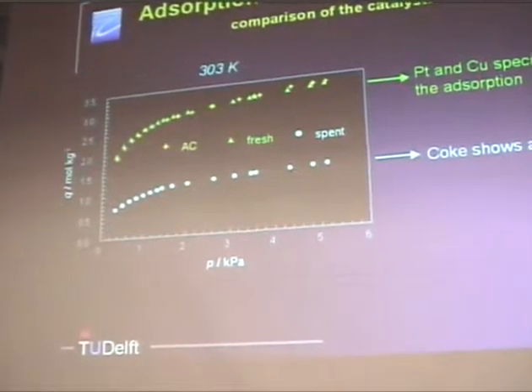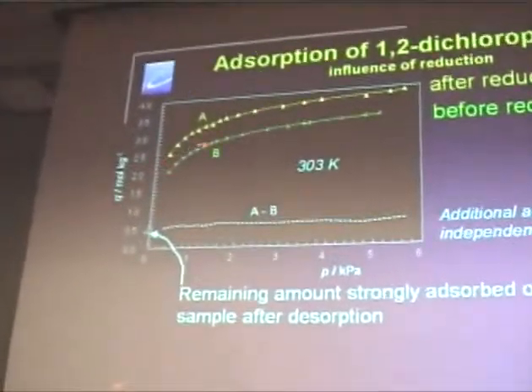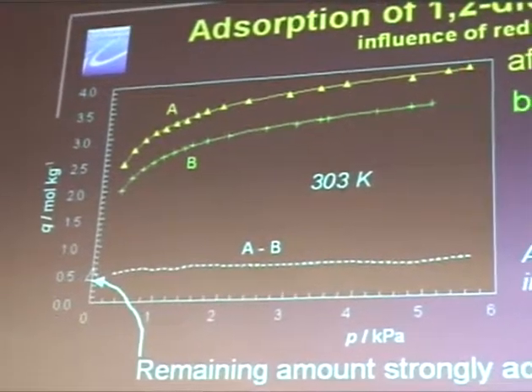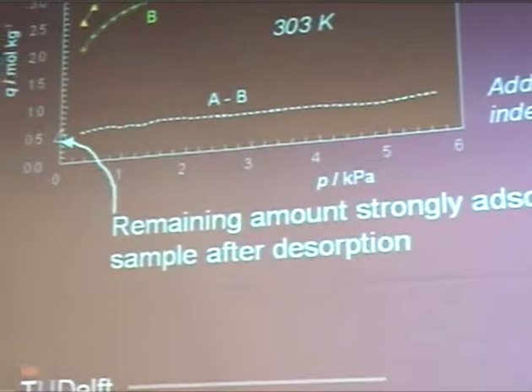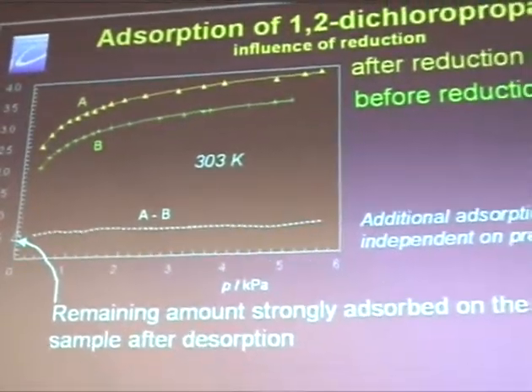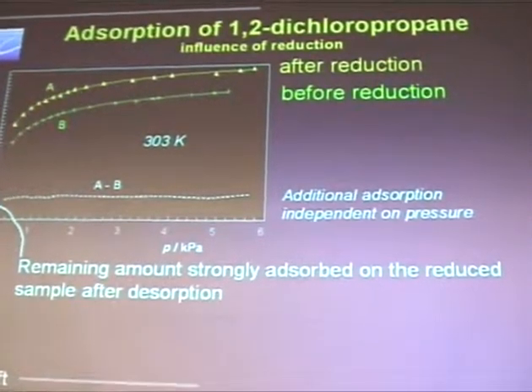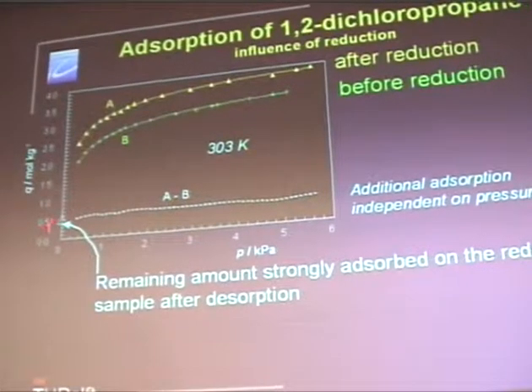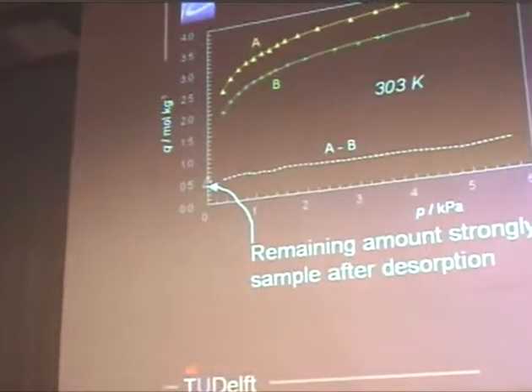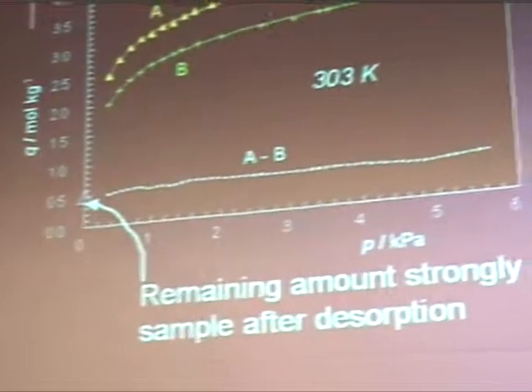So that's logical. But when we reduce the catalyst, we try to reduce the metal part, and we find differences. Before reduction is the green curve; after reduction we have more adsorption, and that ends up at about 0.5 mole per kilogram. That's a lot. So you have to accept that you can never explain that by the platinum. You must have a little bit of adsorption on the copper. That's the first conclusion. And it appears in TPD work that this is really irreversibly adsorbed. So the reactant adsorbs on the copper very strongly.